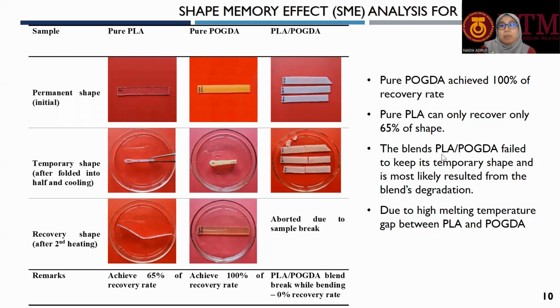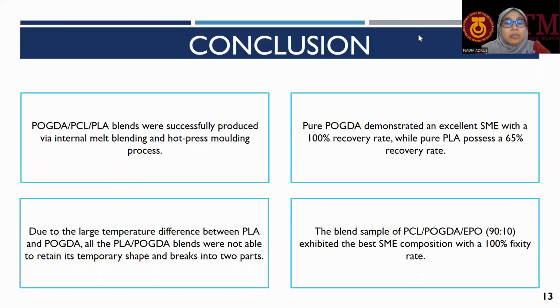But then, since our blend consists of a high percentage of PLA, it also failed to keep its temporary shape. It is most likely because of the blend's degradation. The blend degradation occurs here because PLA actually has a high melting temperature when compared to POGDA. In conclusion, we can say that POGDA, PCL, PLA blends were successfully produced via internal melt blending and hot press molding process. Pure POGDA demonstrates an excellent SME with 100% recovery rate, while pure PLA possesses only 65% recovery rate. Due to the large temperature difference between PLA and POGDA, all the PLA POGDA blends were not able to retain their temporary shape and broke into parts. The blend of PCL POGDA at 90-10 exhibited the best SME, which is shape memory effect, composition, with 100% recovery rate.